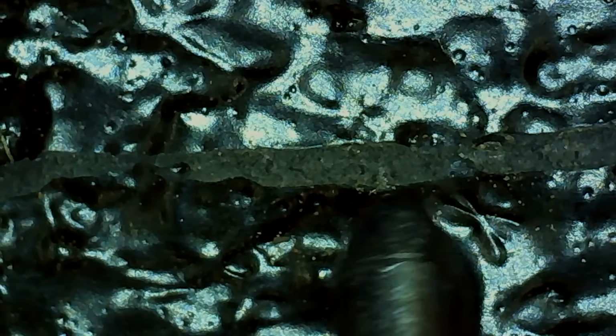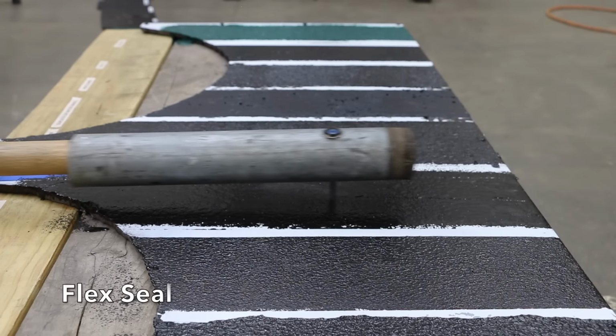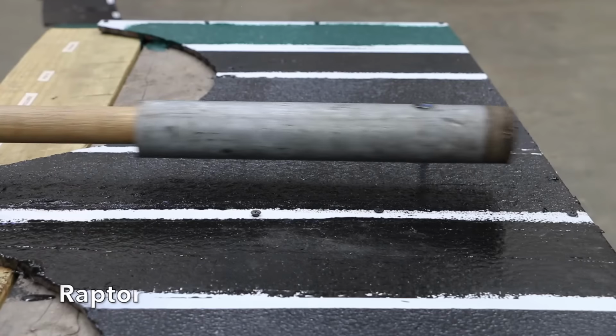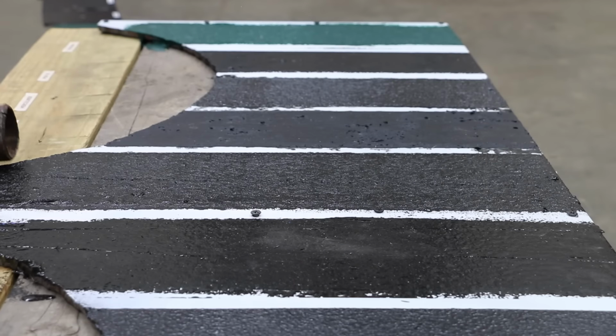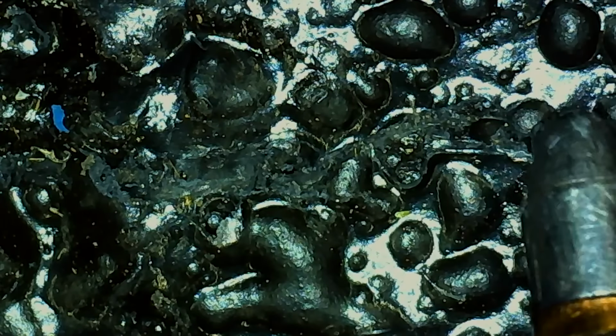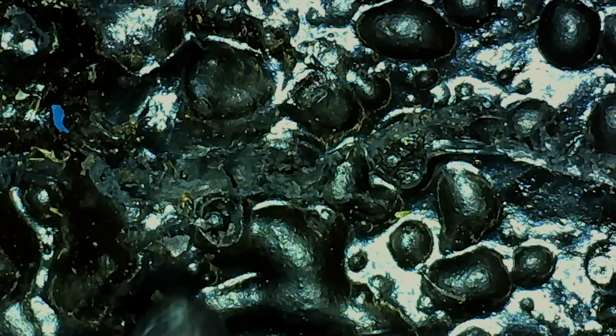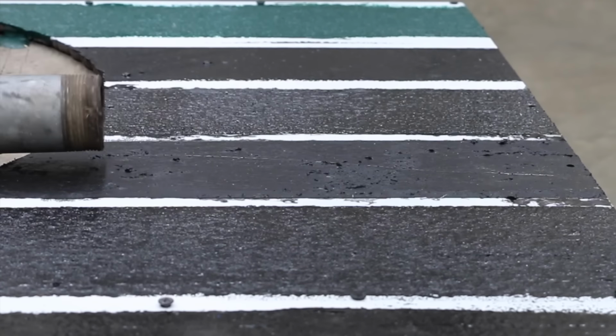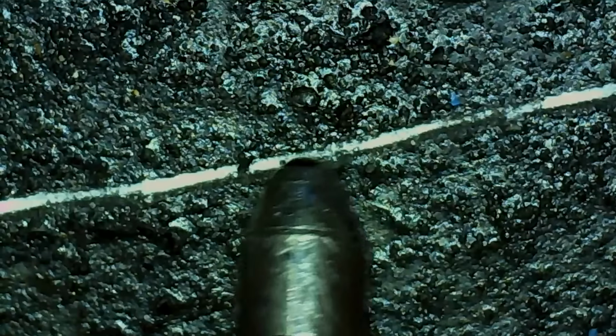The damage to the oil-based Dupli-Color seems to be about the same as Iron Armor with a fairly deep scratch. Flex Seal is a very soft and rubbery coating, and the screw just cut right through the Flex Seal. The Raptor seemed to do just about as well as EGC with a very minor scratch that's even hard to see under the microscope. The screw cut all the way through the water-based Dupli-Color, which seems to have done about the same as Flex Seal.